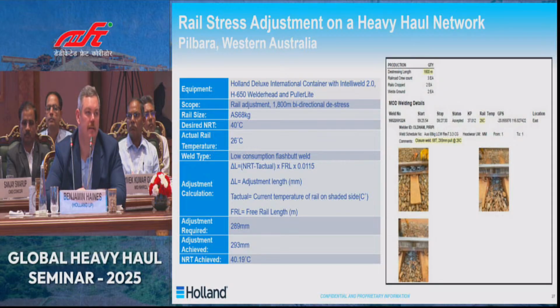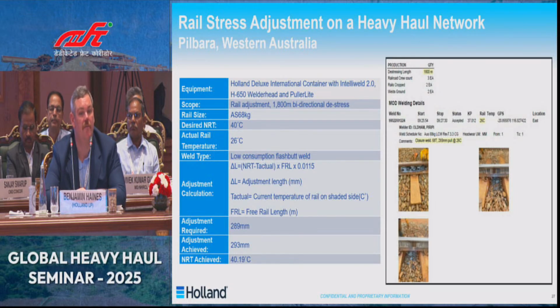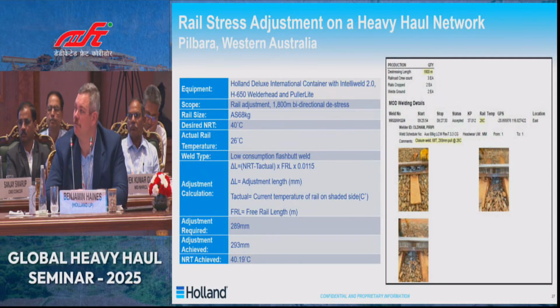So the NRT that we achieved was 40.19 degrees, or within less than 0.5% of the desired. So in terms of quality, that is very, very accurate. I hope you're all able to see to the right, there's a picture of a production report that's standard for every weld within our system.